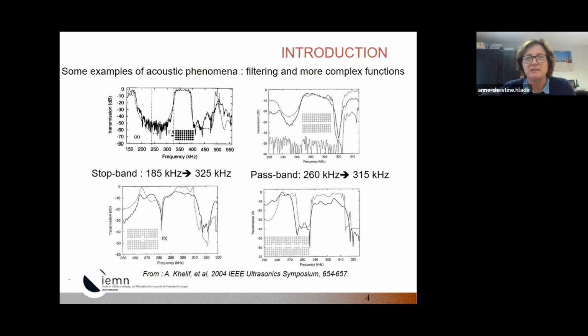And this is a nice illustration made by Abdelkrim Khelif from FEMTO in Besançon. You have steel cylinders in water, a square lattice, with a stop band between 185 kilohertz and 325 kilohertz. If you remove one line of cylinders, then you create a passband inside the previous stop band. And if you remove more cylinders, like in this case, only one, or periodically you remove cylinders, like in the figure here, then you can create a stop band inside the previous passband that was inside the previous stop band. So you can have fun by imagining more complex filtering functions.